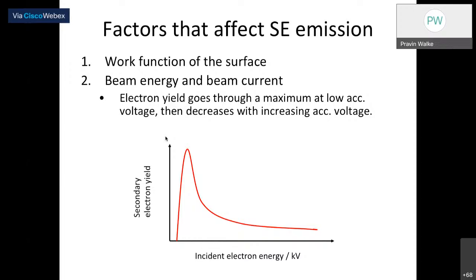The beam energy and beam current are other important factors which affect this secondary electron emission. The emission is maximum when you have a low acceleration voltage, right? And it decreases with increasing accelerating voltage. Here you see this figure: the incident electron energy in kV and the secondary electron yield, right? The secondary electron yield is very high at a low accelerating voltage. But if you further increase the acceleration voltage, you find a decrease in secondary electron yield with increasing voltage, right? So initially at the low accelerating voltage, you find very high secondary electrons, right?